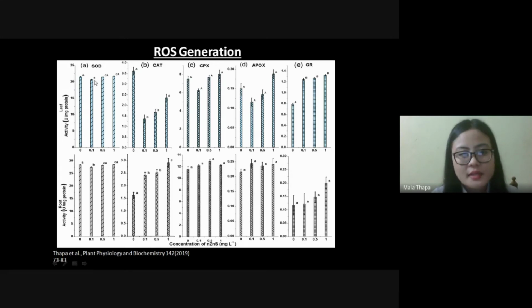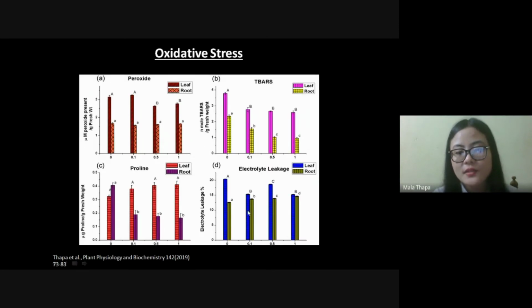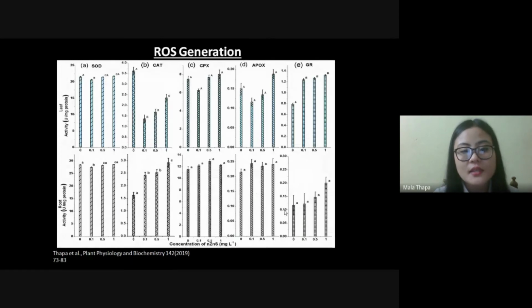Okay, this decrease indicated the antioxidant attribute of zinc sulfide nanoparticle, and with the catalase activity, we have found there was significant increase in root catalase activity. This result corresponds with the electrolyte leakage, as there was also electrolyte leakage increase in roots as well as catalase activity increase in roots. These results confirmed that the organs which come in contact with nanoparticle directly can enhance catalase activity. Okay. But the range of increase of catalase activity and electrolyte leakage were in optimum range, and this range is not enough to produce any kind of oxidative stress inside the plant.